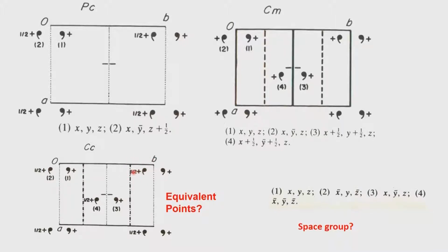Now, what you see here is that, by definition, whenever there is a symmetry operation at 0 and the symmetry operation 1 unit translation, the same symmetry operation will develop at half position. So, using this half position, the C glide, we can generate its corresponding C glide operation. So, that means this now goes into a mirror symmetry, and then it adds on a half in the direction of C, and therefore, we get to this point 4.